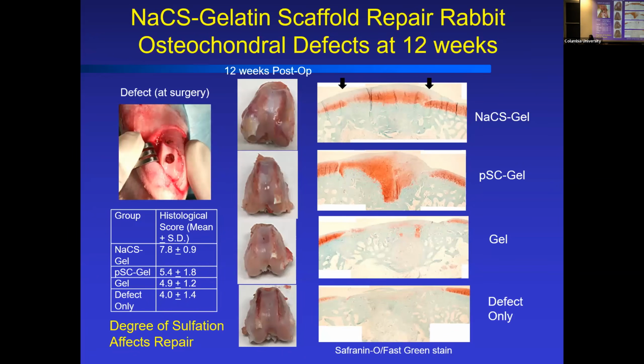Okay, so we've implanted those materials in these osteochondral defects in the rabbit, and we were able to demonstrate that that fully sulfated cellulose performed very, very well. After 12 weeks in these medial condyle defects, we see full integration of the biomaterials, actually resorbed by that time, but we see full restoration of the defect with cartilage as noted.